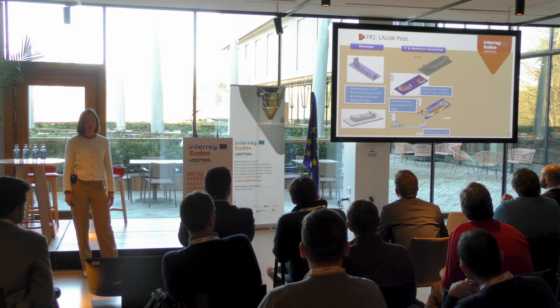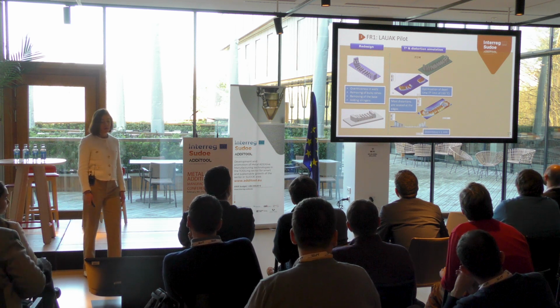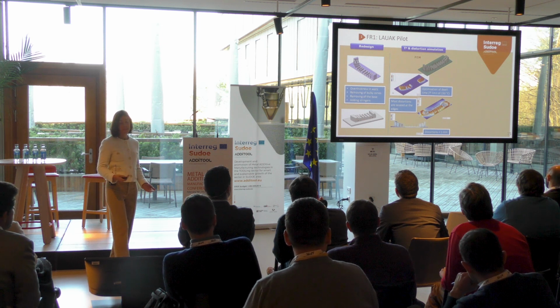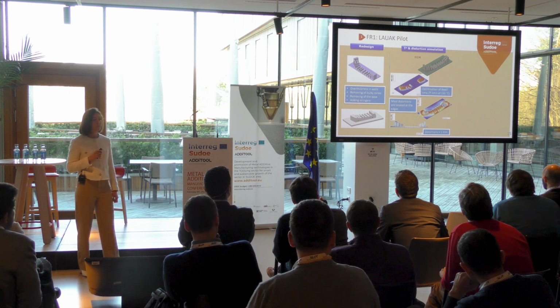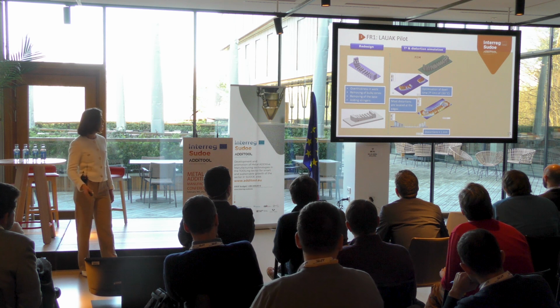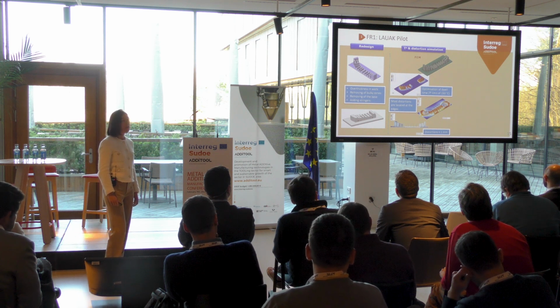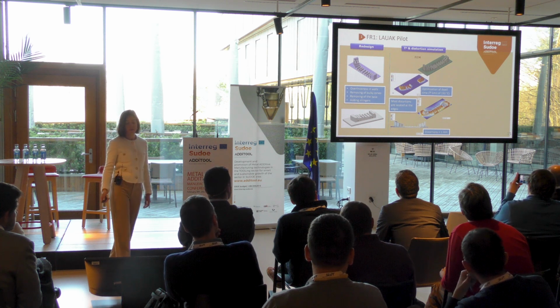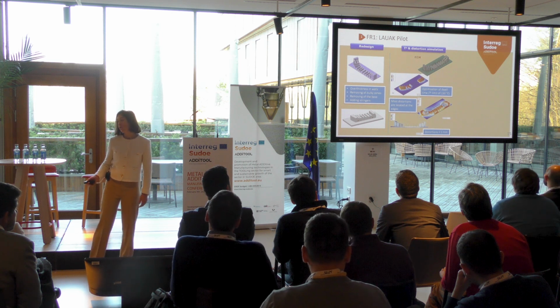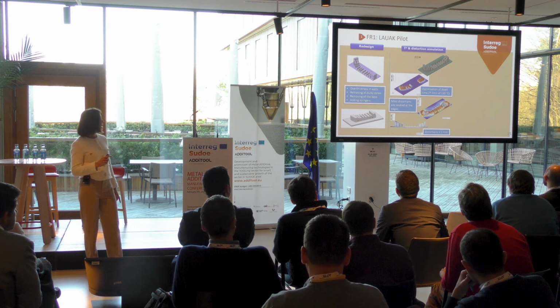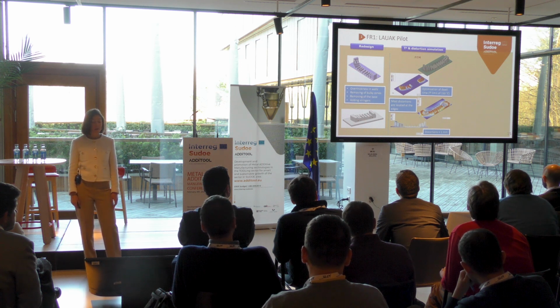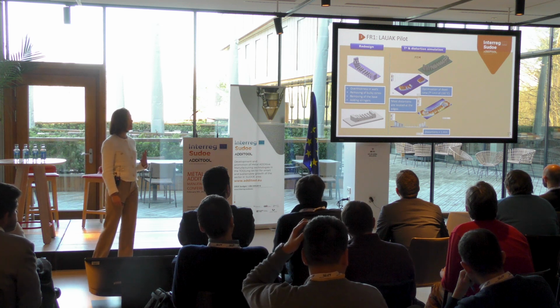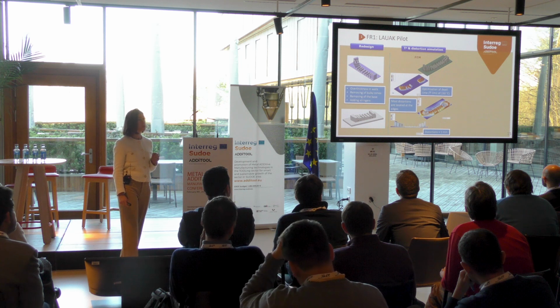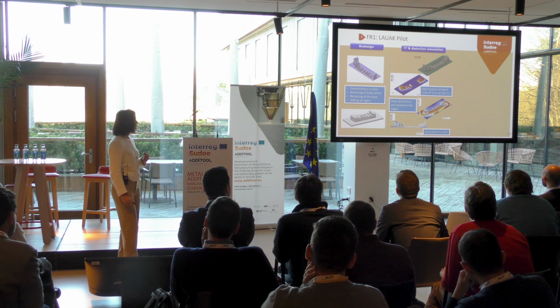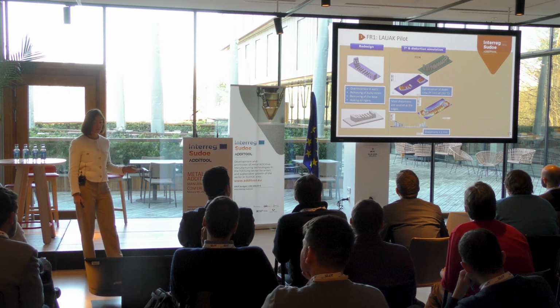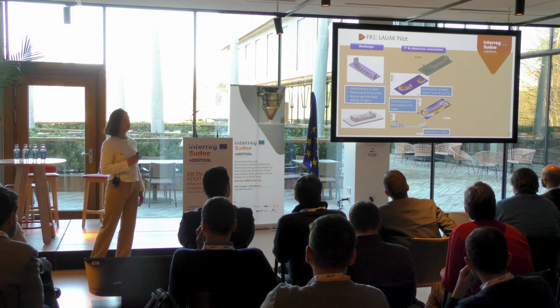We made some thermal and distortion simulations in order to optimize the interlayer dwell time during manufacturing, having temperatures less than 150, which was a limit to avoid collapse or overhangs during manufacturing. We located the distortions in the parts, which were mainly located in the edges of the part. This gave us a clue about which zones need to be kept at cooler temperature to avoid distortions, and the calculated distortions were about 1 millimeter.